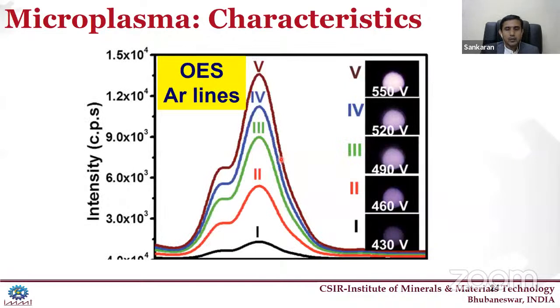And the third thing, from the plasma, we are calculating the emission intensities. Suppose we are using some argon gas, so we can get the argon lines from the optical emission spectroscopic techniques. So this is a very small micro cavity. So we have fabricated a probe, an optical probe made by a fiber, that can take the intensity of the argon plasma, shown here. So these are the argon lines obtained from the optical emission spectroscopy.